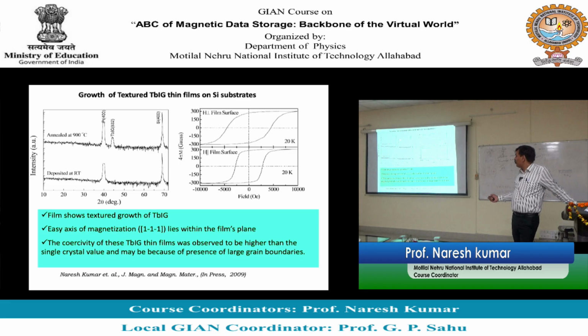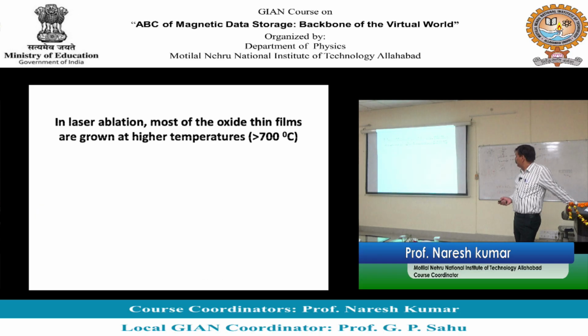So why could we do this? Because we have grown TbIG with 532 orientation, right? So 532 is out of plane, and we could see the easy axis of magnetization. See, if 532 is out, then you have 111 within the plane, right? 5 minus 3 minus 2 goes to 0, right? That way we could observe the easy axis of magnetization within the film plane. This was immediately accepted. Just one film, one experiment.